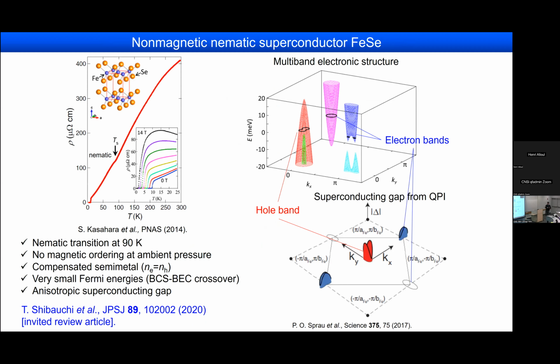Okay, so let's look at the experiment. I'm an experimentalist, so I'm not a theorist. We are studying this iron selenium-based superconductor, which is very interesting. And it has a so-called nematic transition at 90 Kelvin, below which you have electron anisotropy within the plane. And what is interesting here is that we have no magnetic ordering down to zero temperature, meaning that this electron nematicity is a pure nematic phase without magnetism. Okay? And from the quasi-particle interference measurements, the superconducting gap has been shown to have a very strong anisotropy. It has a deep minima, or maybe it has a node in the superconducting gap.